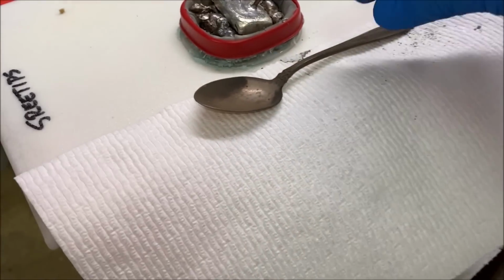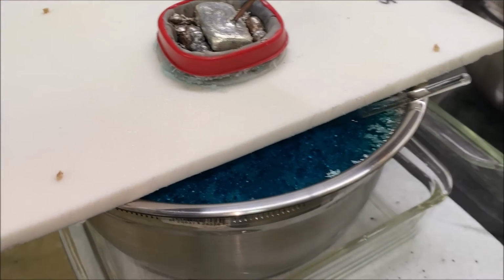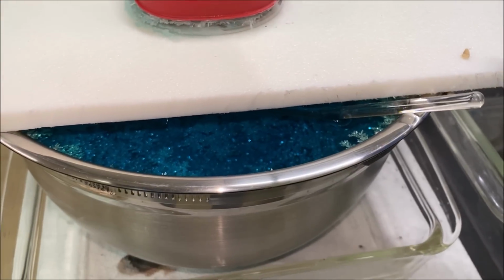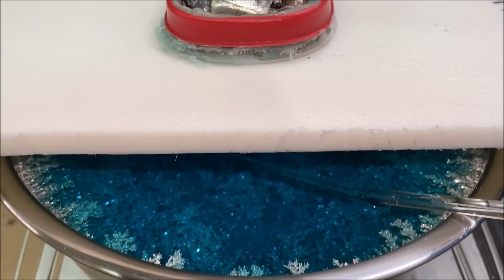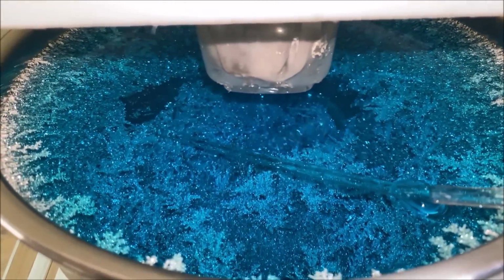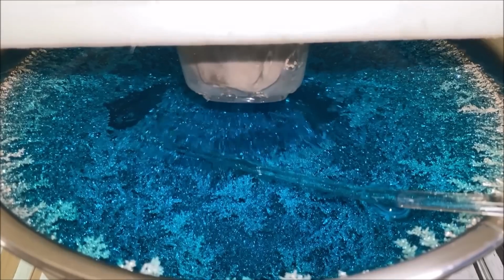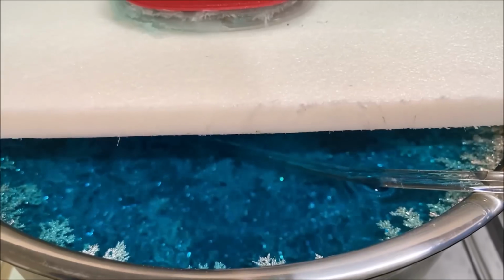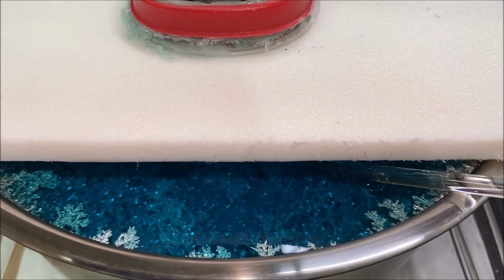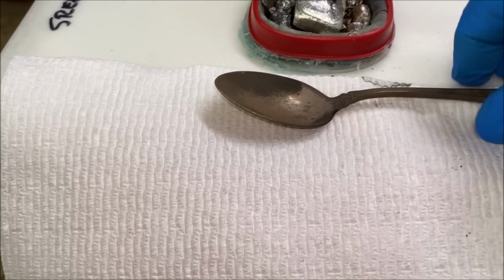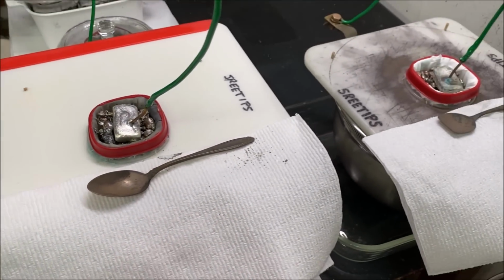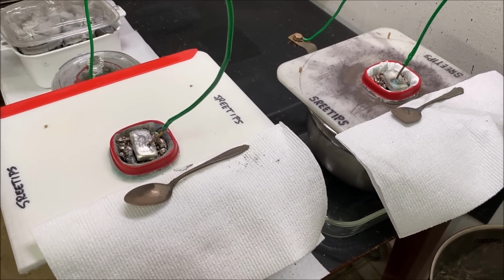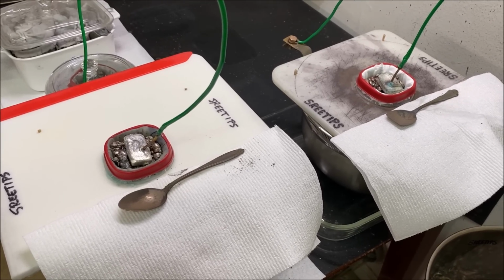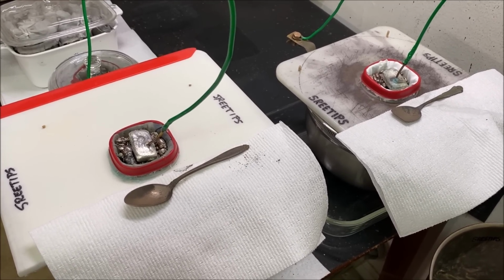And then on this one, this is silver cell number 2, the one that we just built here recently. This has been running for about a week, about 10 days. And there's the silver that we've got accumulated in silver cell number 2, the new one. And we'll let both of these run and get just as full of silver crystal as we can. And then we'll do a harvest on both silver cells at the same time and see what kind of yield we're going to get with both silver cells in operation.